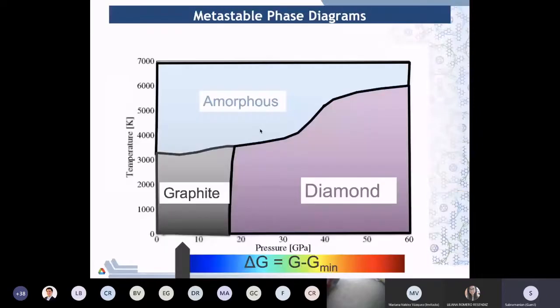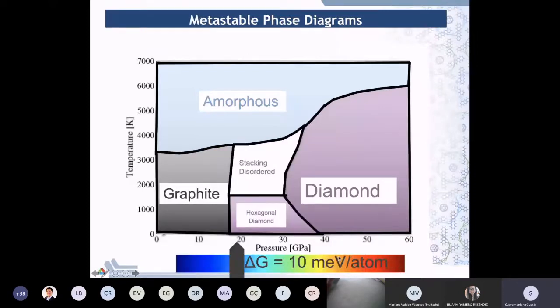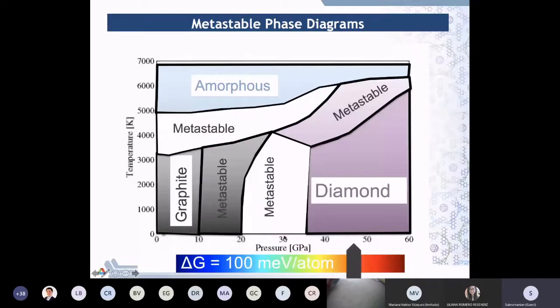So our vision is that when you have a phase diagram, this is typically what you will find for carbon. If you look at a carbon phase diagram, you will see graphite, okay, pressure against temperature. You will find graphite, diamond, and amorphous regions. What we want to do is to introduce a free energy scale that allows us to cut a slice through this landscape. So if we are interested in a material that is 10 meV per atom above the most stable phase, we should be able to see what those phases are. So in this case, if you go 10 meV per atom above the most stable phase, you will see stacking disordered and hexagonal diamond. If you go even higher, you will start seeing more metastable phases. So the idea is that you can start accessing these phases by providing external heat input or any other form of stimuli that allows them to be pushed to that local minima.